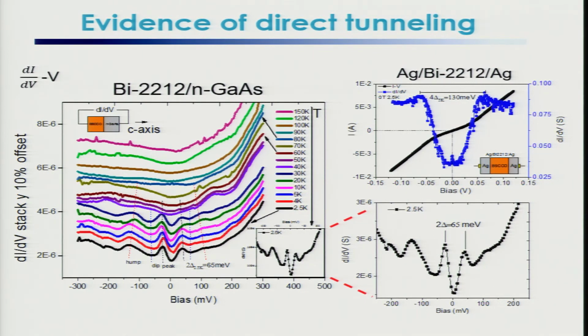So we have done a lot of spectroscopy. This is silver. This is just looking at a piece of BSCCO alone with silver on both sides and showing that the gap again is 4 delta, because we have 130 millivolts for that difference. So let me show one final graph.